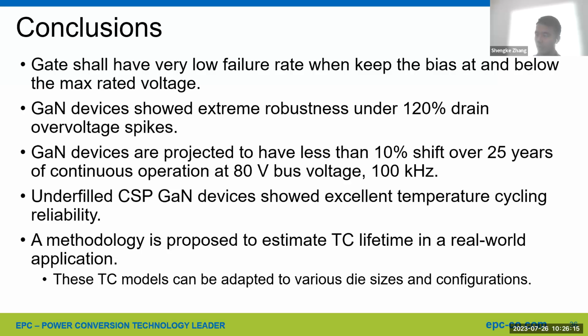Next, using our resistive load hard switching circuit, we found that GaN devices are projected to have less than 10% shift over 25 years of continuous operation at 80 volt bus voltage and 100 kilohertz. Next, in our temperature cycling section, we showed that underfilled chip scale package GaN devices showed excellent temperature cycling reliability. Based on the test to fail lifetime equation, we developed a methodology to estimate TC lifetime in a real world application. These temperature cycling models can also be adapted to various die sizes and configurations.